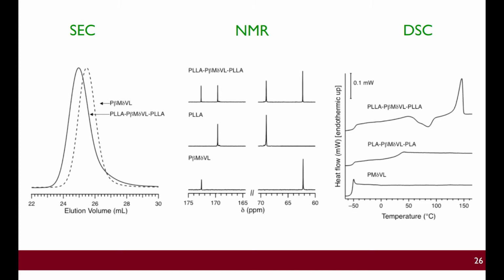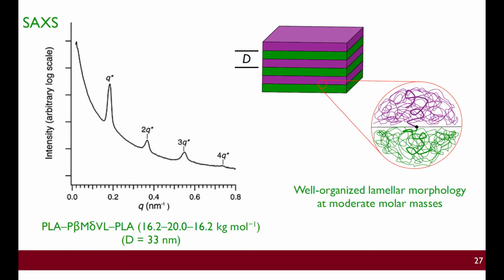And then the differential scanning calorimetry tells us that the mid block, in fact, does have a very low glass transition temperature, where the PLA block has a higher glass transition temperature. In this case, a little less than 50, but you can make semi-crystalline variants that lead to crystalline PLA that melt well over 140 degrees Celsius. So there's no question that we were able to make these tri-blocks, and they're well characterized molecularly. They also self-organize into these nanostructures that I showed you before, so they act and behave like normal block polymers.